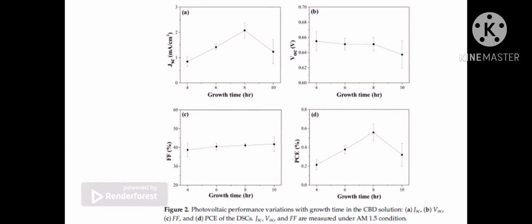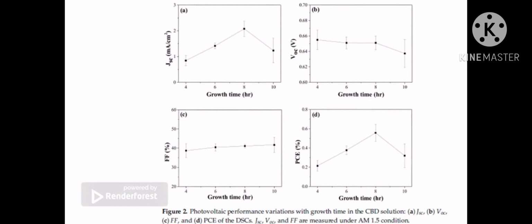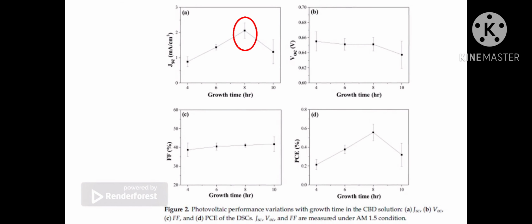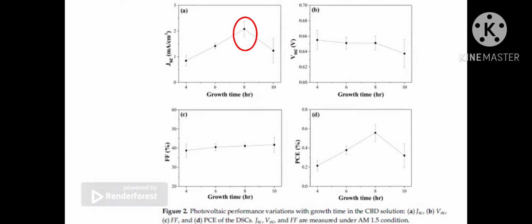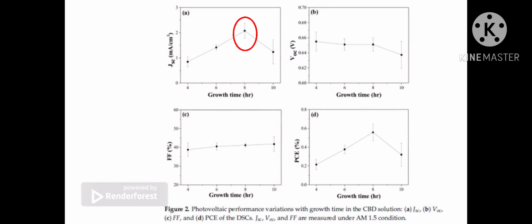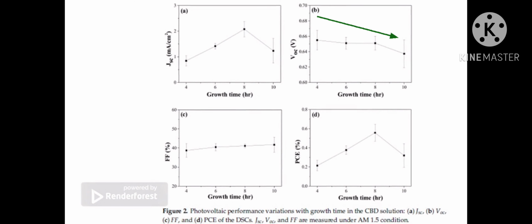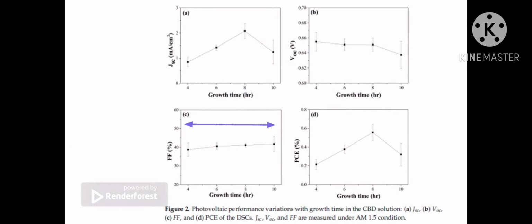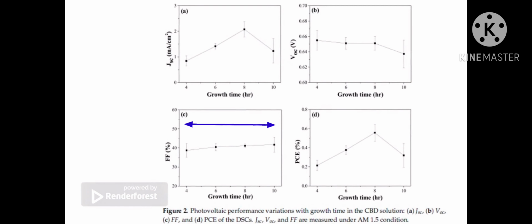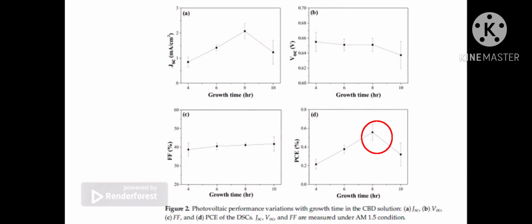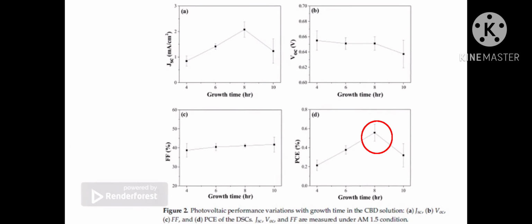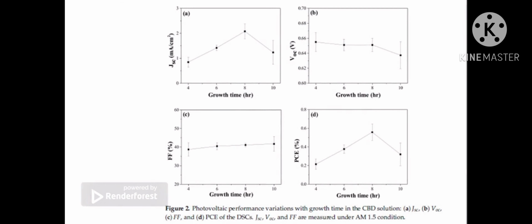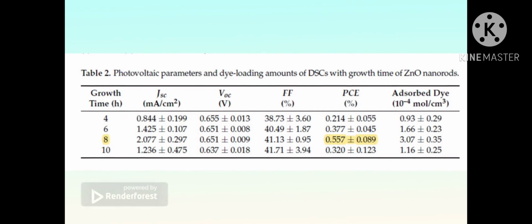As you can see, this is the cell performance with growth time. An increase in the JSC was observed with increasing growth time from 4 to 8 hours. The VOC value decreased with growth time. No variation was observed in fill factor. And the highest PCE value was recorded at growth time of 8 hours. What is interesting here? At 8 hours, it gives the highest value of PCE.